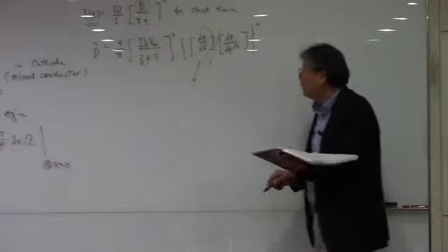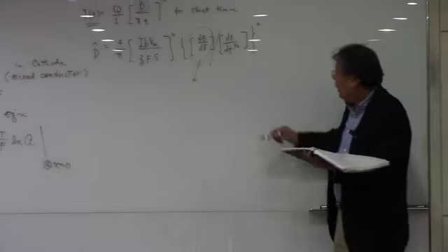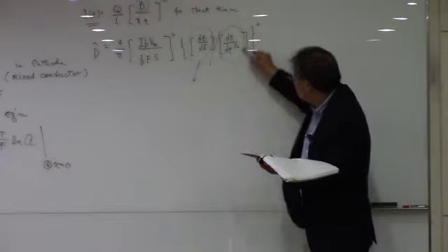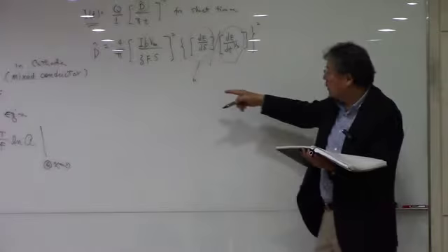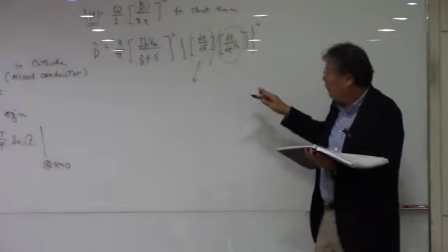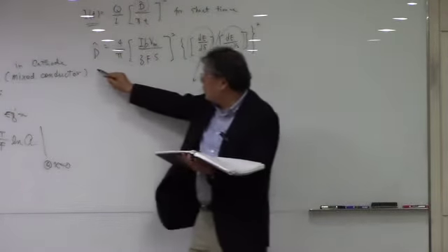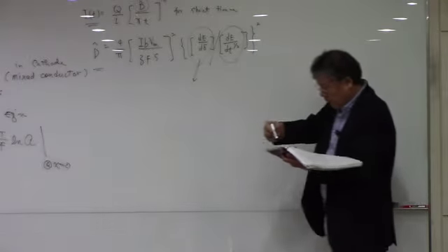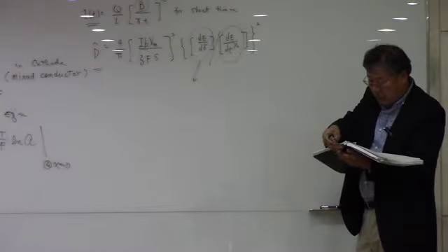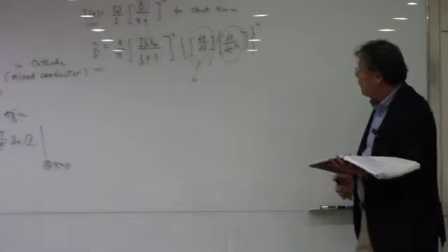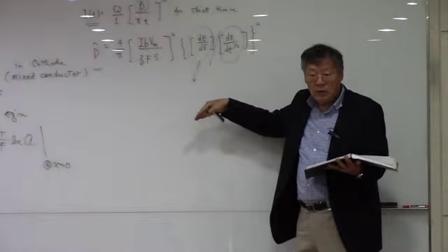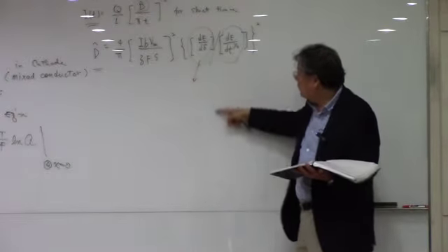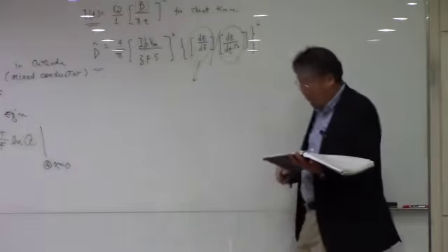And this is the slope in the coulometric titration curve. And this is the voltage change that you monitor in the galvanostatic method, okay? So basically you can determine the diffusion coefficient. Of course, this is the result at the early stage, where dE over d delta is linear, okay? Then you can determine the diffusion coefficient.